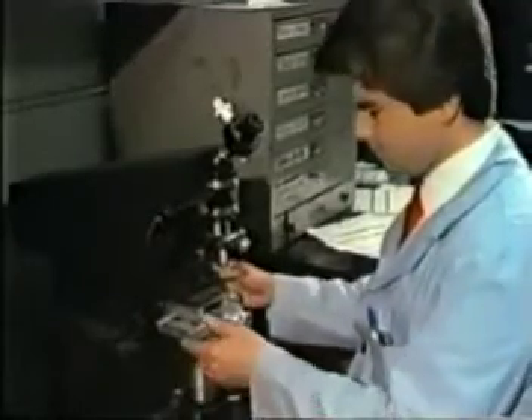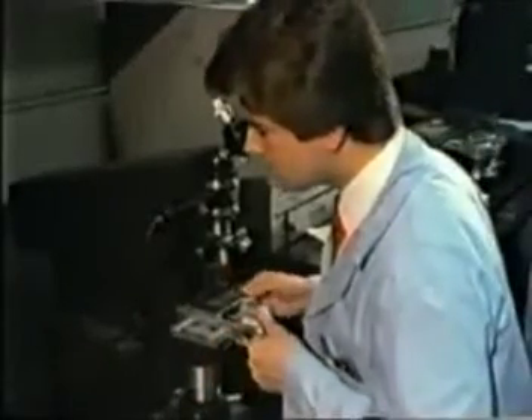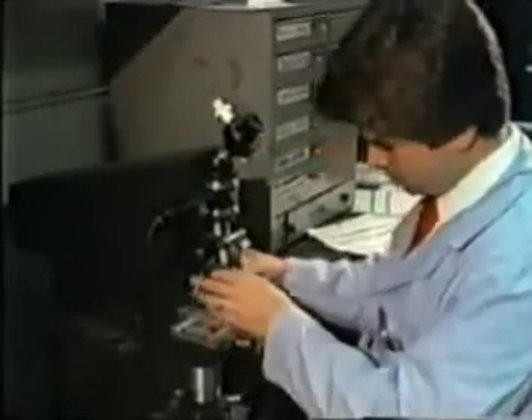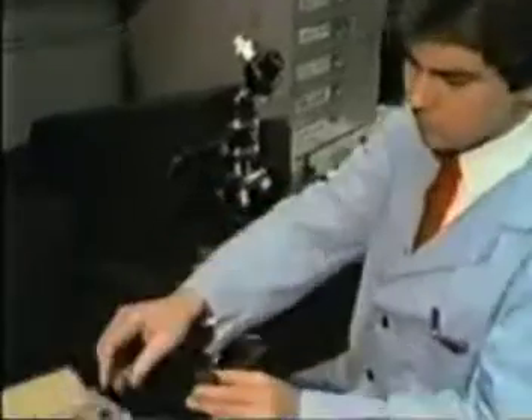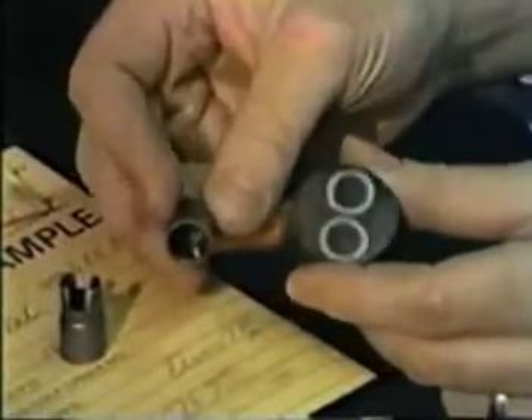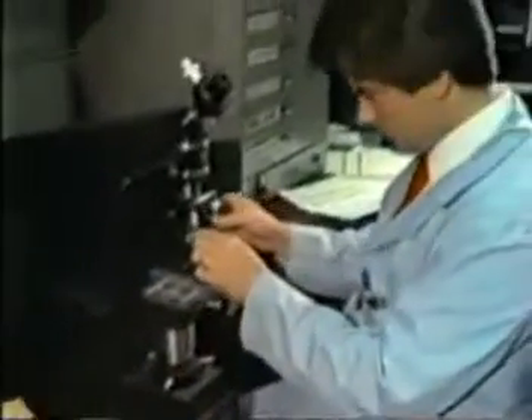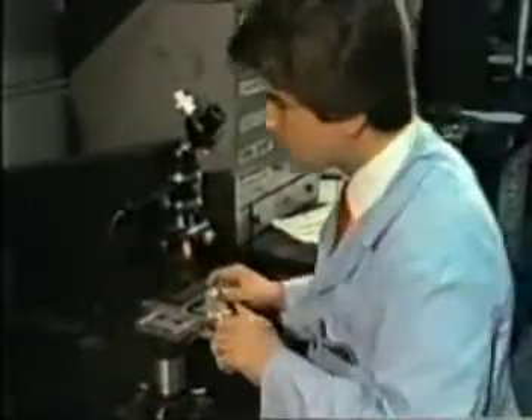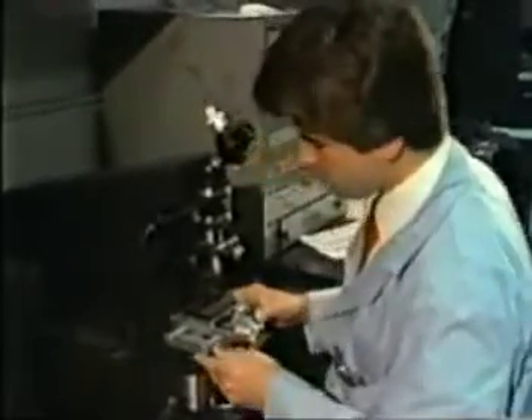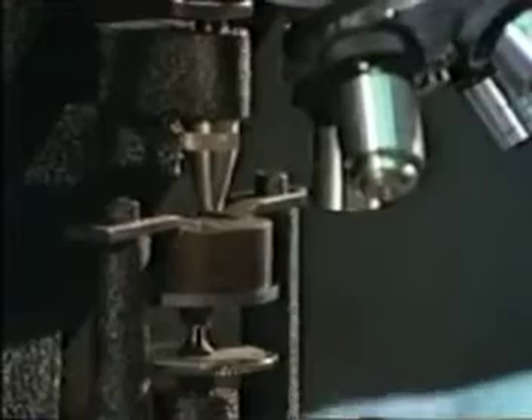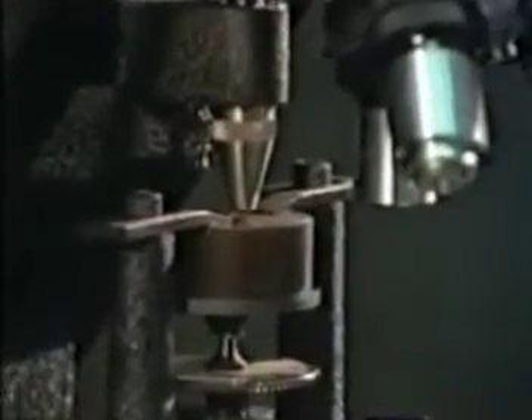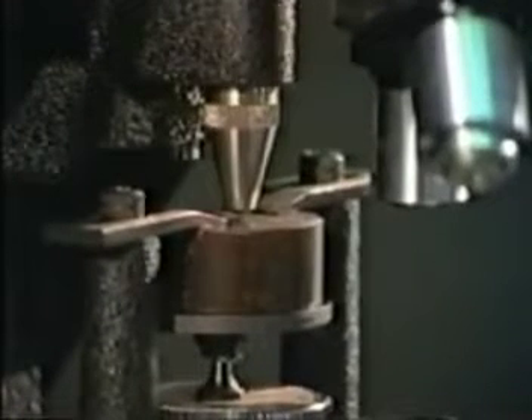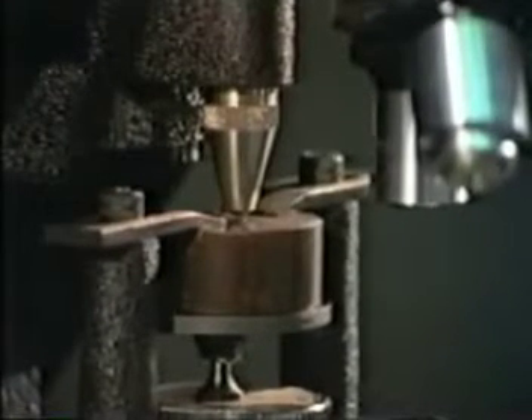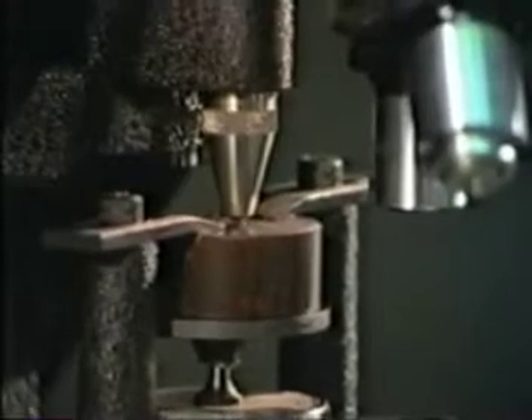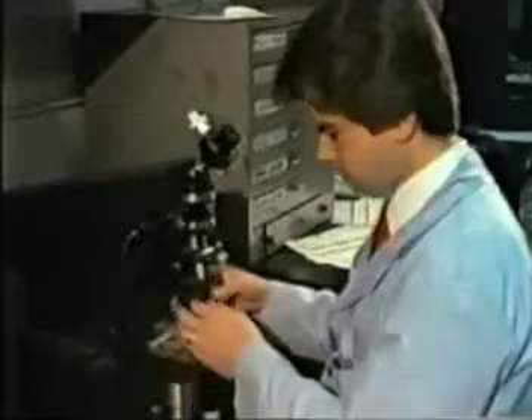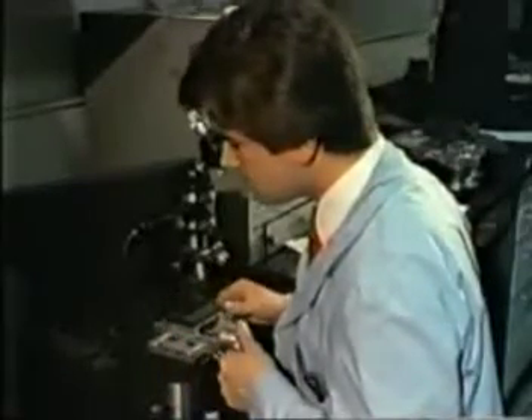In some cases, the exact depth of hardening must be determined. When required, this is accomplished by using a Tukon micro hardness tester. The section measured is cut, mounted in plastic, polished, and positioned on the machine. Then, through the use of a microscope and a micrometer table on which the section has been placed, the exact point that is desired to be checked for hardness is located. By using a specially shaped elongated diamond indenter, a very light load can be applied. The length of the impression is then measured using the microscope and converted to a hardness value. Again, the smaller the indentation, the harder the metal.